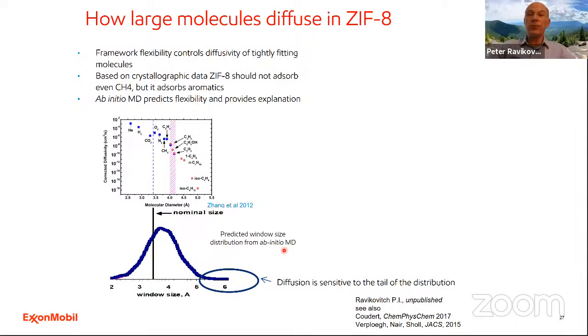So here is the experimentally measured diffusivity. This is from Ryan Lively and Bill Koros groups, the diffusivities of different hydrocarbons in ZIF. And as you can see, for the range of molecules which readily diffuse, the size of those molecules exceeds the size of the window by at least about 1 angstrom.